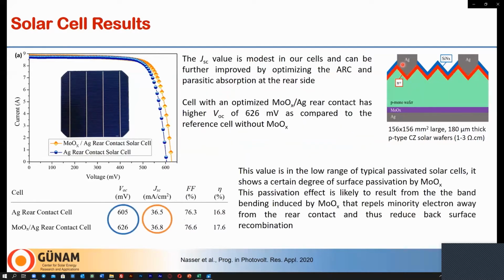On the other hand, if you look at the short circuit current density for the solar cell with molybdenum oxide and silver, it's quite low and needs to be optimized further. And the VOC values are still in the low range of typical passivated contact solar cells, and it can certainly be improved by inserting some passivation layer between molybdenum oxide and silicon. A more important point here is the EQE response in the infrared, where we have our molybdenum oxide and silver contact, especially above 850 nanometers. So we have enhancement in EQE here, which further demonstrates the benefits of using molybdenum oxide at the back side.